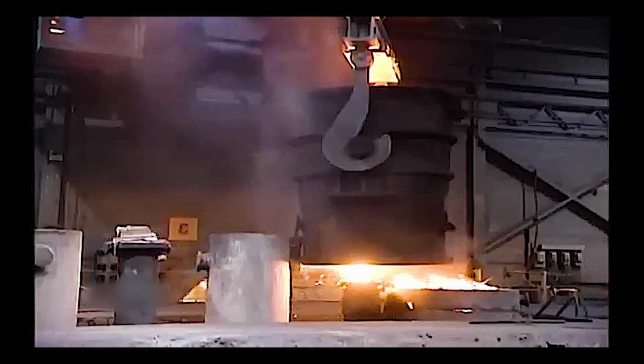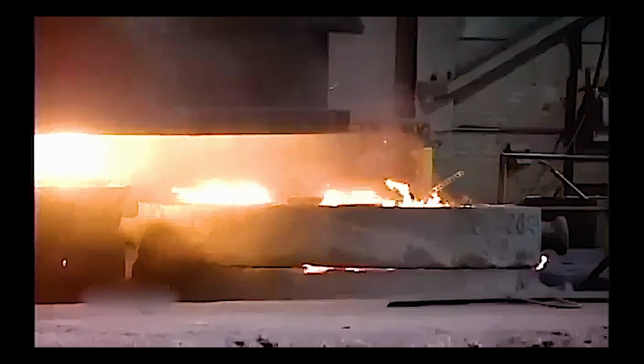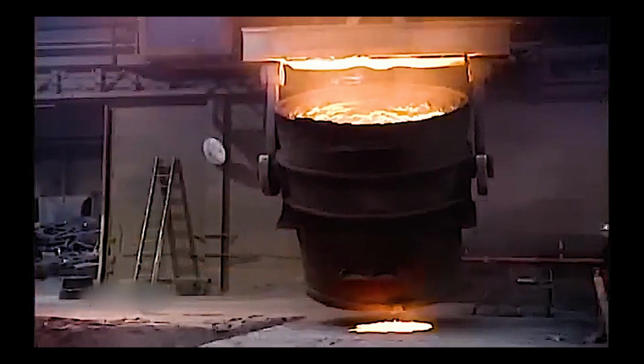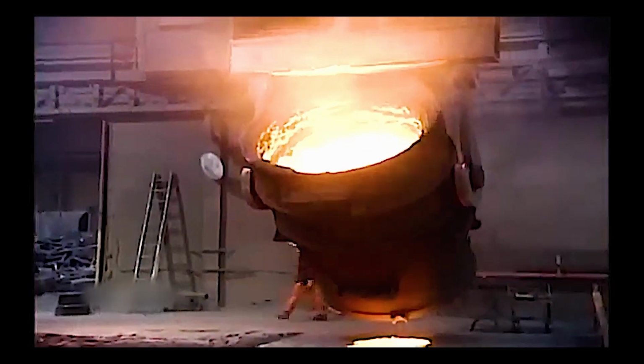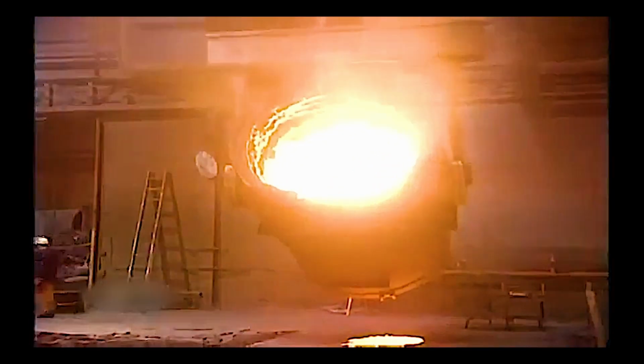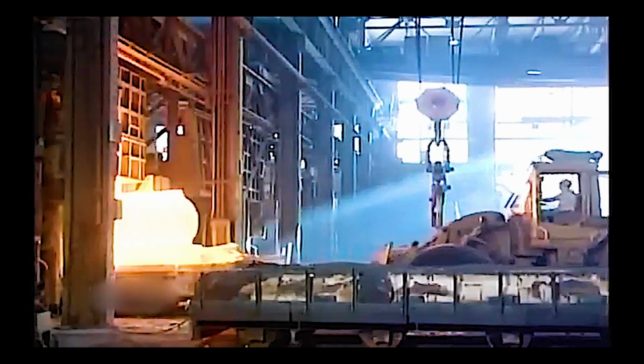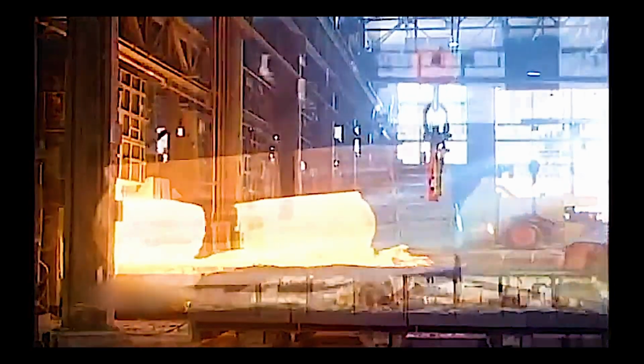The metal flows out from the bottom of the ladle into a mold, a process called bottom pouring, which ensures a smoother casting. This forge can create ingots weighing up to 42 tons. After solidifying, the mold is inverted to extract the ingot, which is then reheated to 1,200 degrees Celsius over 12 hours, making it soft enough for shaping.